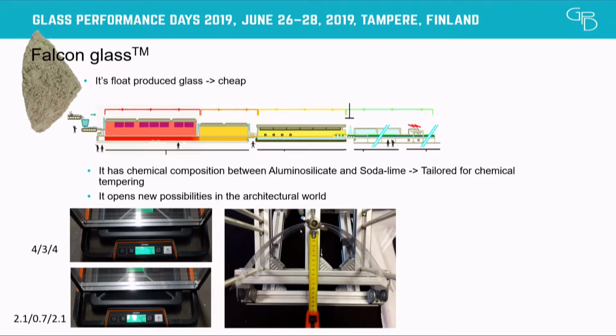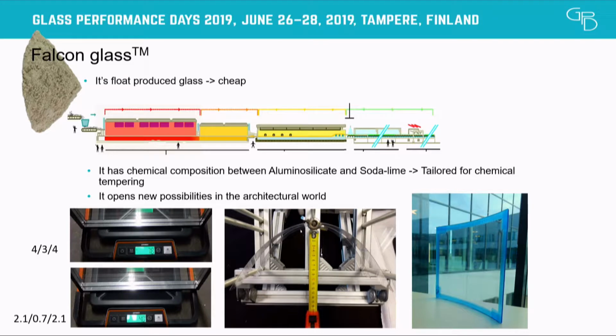And this is another interesting thing that we did, which is bending with lamination. So you take 2 panels of 0.5 millimeter glass and put them in the oven, you laminate them flat, and then you can heat up your PVB again, and it will keep the shape into the curve. There are lots of things to further understand on this subject, which has clearly to do with the spring back effect, but this is what we are doing at the moment.